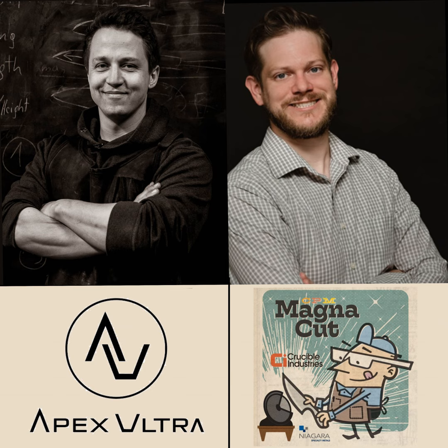Because if it happens in the first stage, the company that makes the first stages, they're just going to redo it, and that's it. If it's in the second stage, it's also not as bad, but in the third stage, it gets really expensive. So hot rolling is definitely the riskiest step for us. And we've had a couple of different, minor or major losses during that stage. And there's also a certain risk that they just basically lose a billet because it doesn't hit.